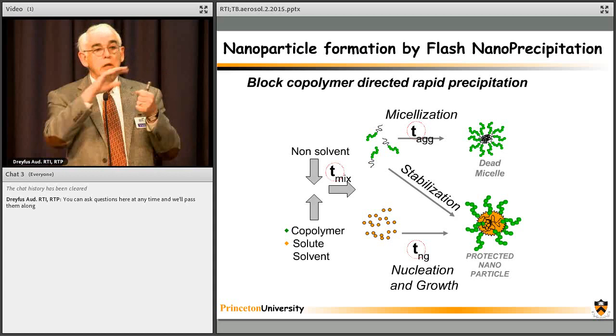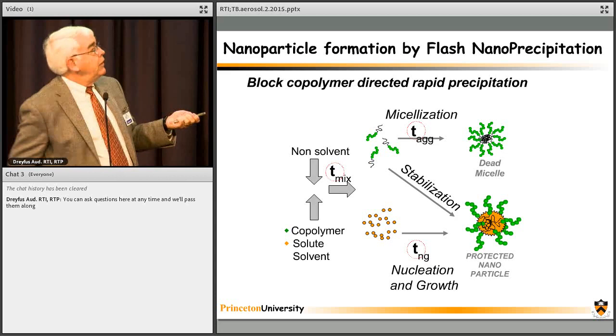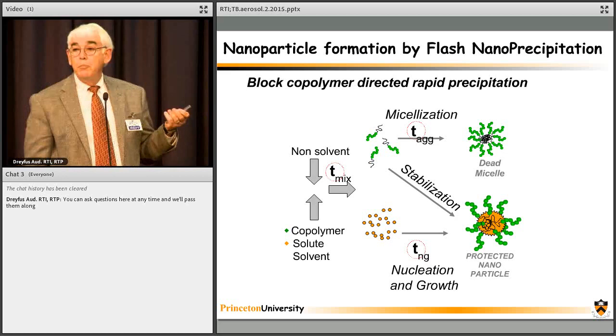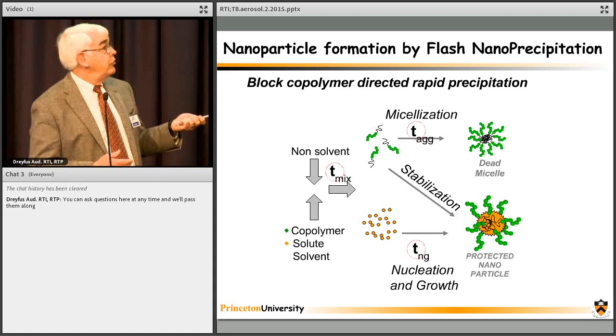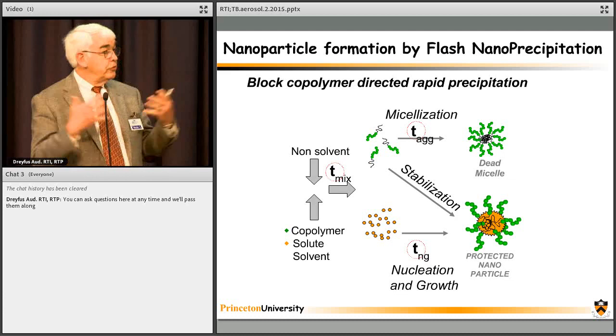If this process, micellization, is too fast, then what you end up with is forming micelles. There is not enough polymer to sterically stabilize the particles, and they will grow without bounds. Or if this process is too slow, these particles just grow way too big before you've adsorbed enough polymer on them to stop aggregation. So controlling those two timescales is how we control the particle size.